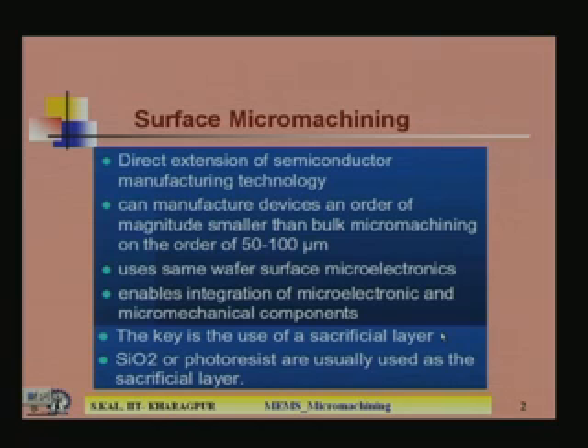Now, surface micromachining is a direct extension of semiconductor manufacturing technology. Direct extension means it is coming from the normal etching which is used in VLSI processing. Bulk micromachining is not a direct extension, because the normal VLSI process does not require etching up to 300 micron, 400 or 500 micrometer. But in surface micromachining, the etching is in the range of a few microns, 1 micron or 2 micron, in some cases maybe 500 angstrom also. So, that is why they mentioned that surface micromachining is a direct extension of the semiconductor manufacturing process, because the etching depths are more or less the same as the VLSI process.